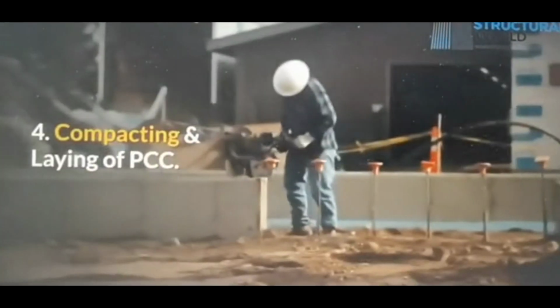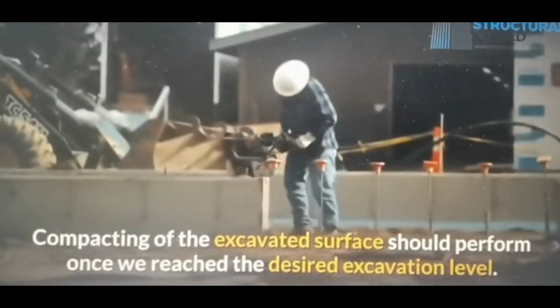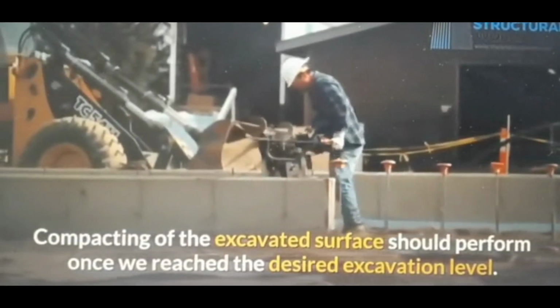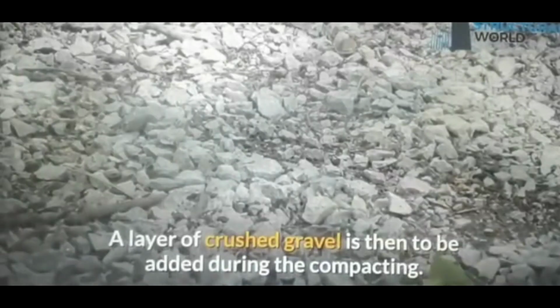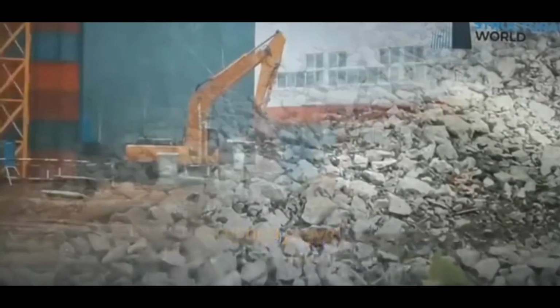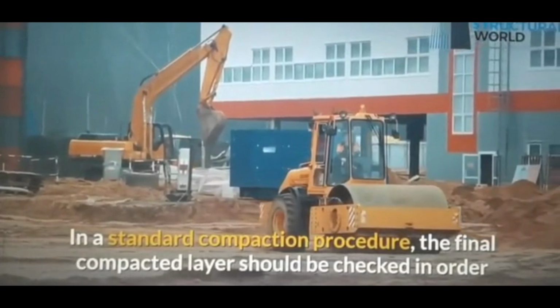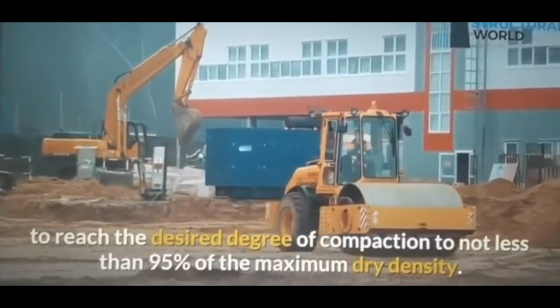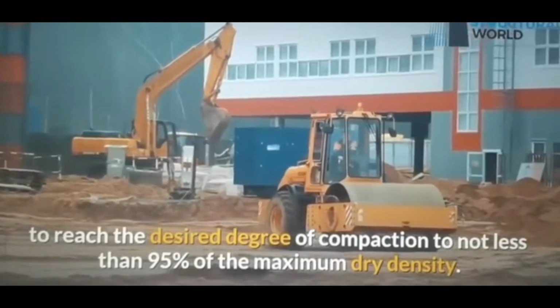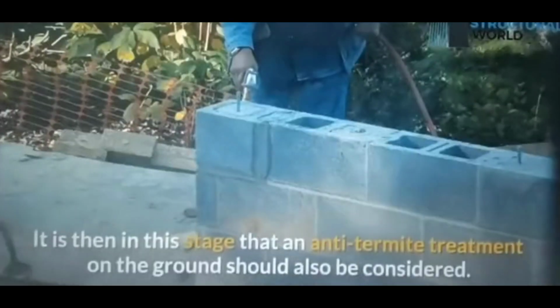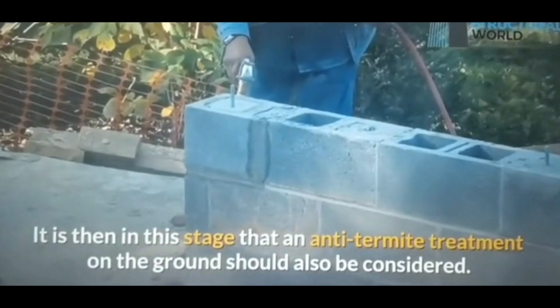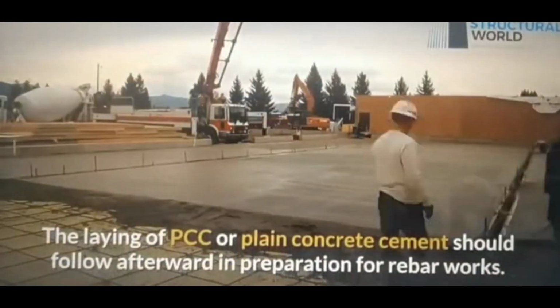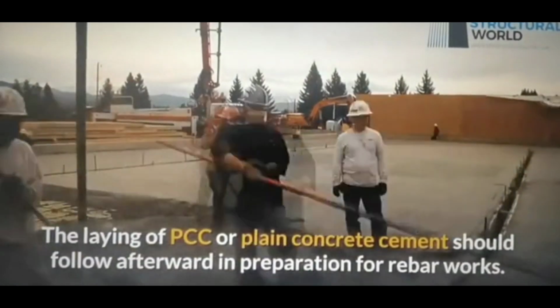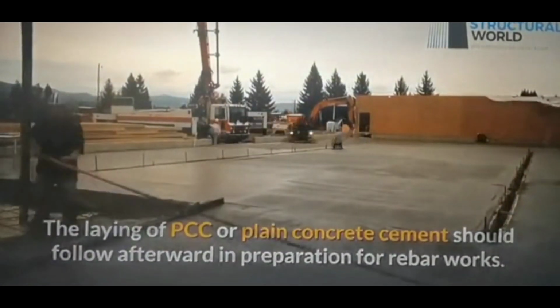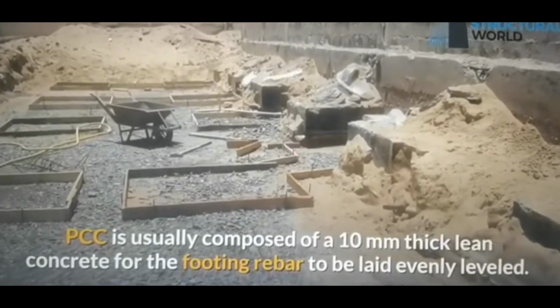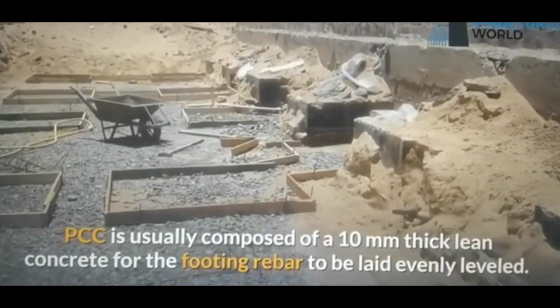4. Compacting and laying of PCC. Compacting of the excavated surface should be performed once we reach the desired excavation level. A layer of crushed gravel is then added during the compacting. In a standard compaction procedure, the final compacted layer should be checked to reach a degree of compaction of not less than 95% of the maximum dry density. It is in this stage that an anti-termite treatment on the ground should also be considered. The laying of PCC or plain cement concrete should follow afterward in preparation for rebar works. PCC is usually composed of a 10 mm thick lean concrete for the footing rebar to be laid evenly level.